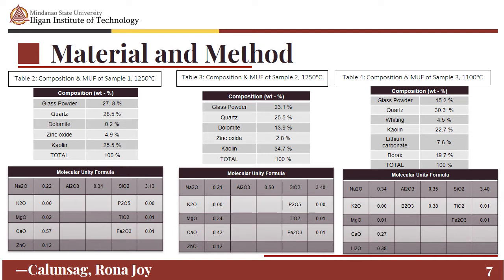Same goes for the table 3 for the composition of sample 2 fired at 1250 degrees Celsius. The glass powder has 23.1%, the quartz has 25.5%, the dolomite has 13.9%, the zinc oxide has 2.8%, the kaolin has 34.7%. And for the molecular unity formula, or the Seger formula, we have the Na2O of 0.21, the K2O